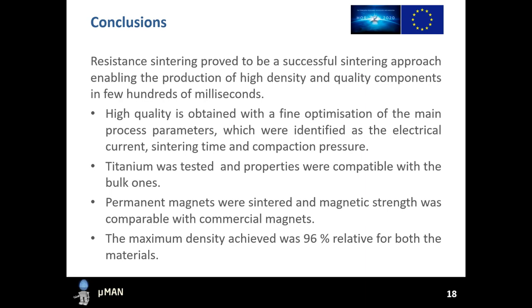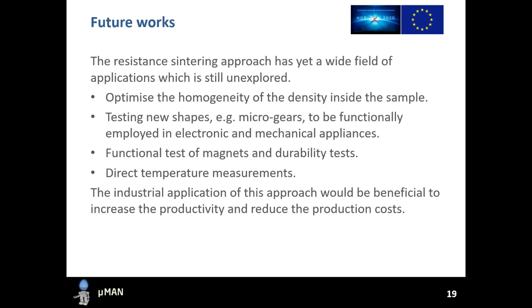Titanium was tested and properties were compatible with the bulk ones. Permanent magnets were sintered and the magnetic strength was comparable with commercial magnets. The maximum density achieved was 96% relative for both the materials.